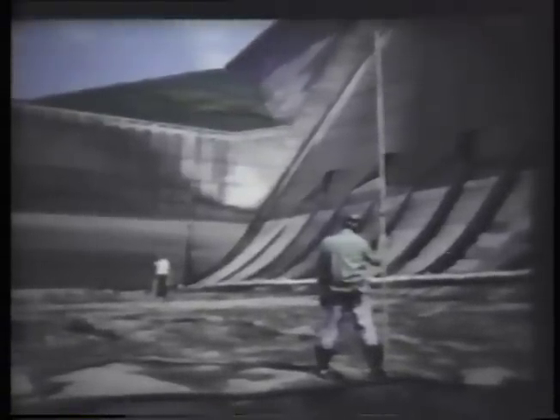At Kinzua, the stilling basin is a large area, about 204 feet wide by 180 feet long, with 5-foot thick slabs of concrete. It was originally placed in operation in 1966 and was made of good quality concrete with 6-inch sized aggregates. By 1973, the combination of high-velocity water flow and the presence of debris in the basin had eroded the concrete surface and caused general erosion, with holes as much as 3 feet deep.